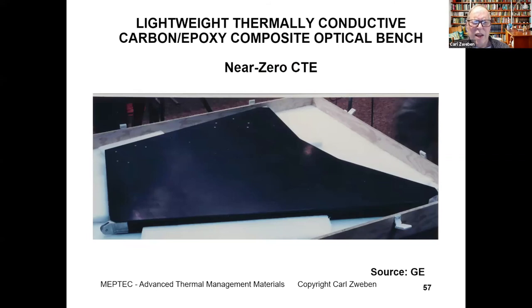Finally, in terms of applications, I mentioned that support structures are also an area of application of advanced materials. Here we have a composite optical bench for a spacecraft that is composed of thermally conductive carbon fibers in an epoxy matrix. And the big advantage here is that it gives you a near zero CTE and significant weight savings compared to the baseline aluminum. So again, we have a wide variety of materials with unique properties that give the design engineer a great potential for improved performance and weight savings.